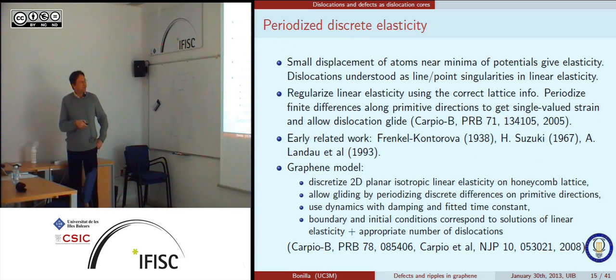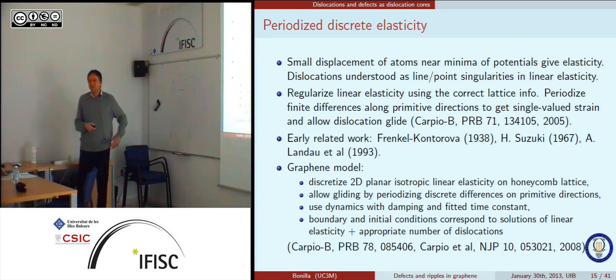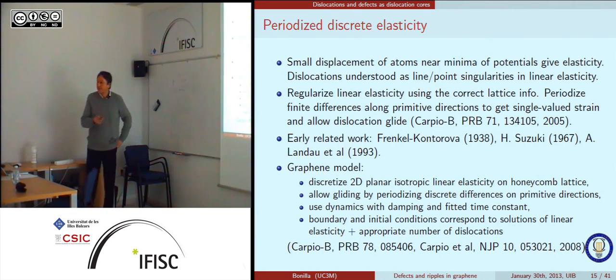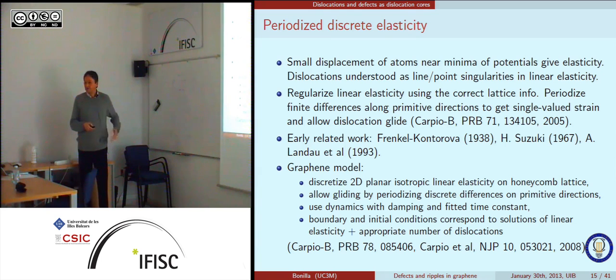We discretized the 2D isotropic linear elasticity on a honeycomb lattice. So we just replaced the derivatives by appropriate finite differences on the primitive directions of the lattice. Then when a dislocation glides, we avoid having to keep track of which atom is neighbor to which one by just replacing the gradient of the displacement by periodic functions that are periodic along the primitive directions. And we used just classical dynamics with damping and fitted the time constant to the experimentally measured evolution of the defects. Now the boundary and the initial conditions that we use are given by the known solutions of classical elasticity.